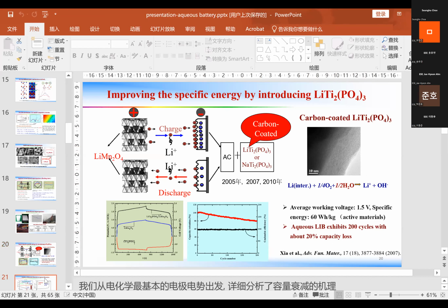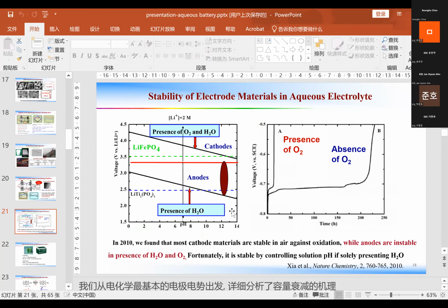So what happened? In 2010 we published one paper in Nature Chemistry. We found that, like most other materials such as lithium iron phosphate, if oxygen and water are present, the oxygen and water will oxidize this lithium titanium phosphate. For the cathode material, it's no problem. The anode is a bigger problem. Even if we use carbon materials, if oxygen is present, it will be oxidized.